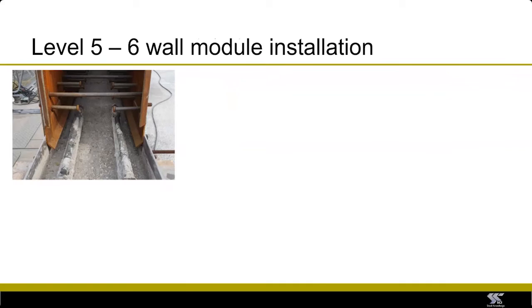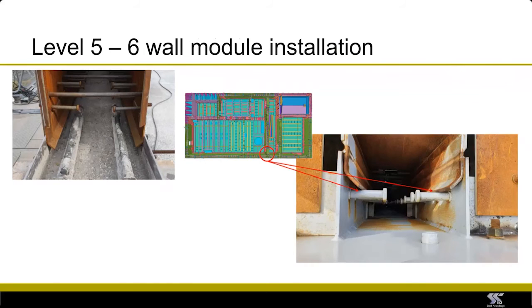For the upper level modules, we used welding. So some of the modules were fillet welded, some were butt welded. You can see here a module that has been installed with guide plates, which also act as backing plate for the fillet weld. Now, tolerances start to become more important for the welded modules. So here you can see an example of a module where there is virtually zero tolerances between the backing plate and the shear studs.